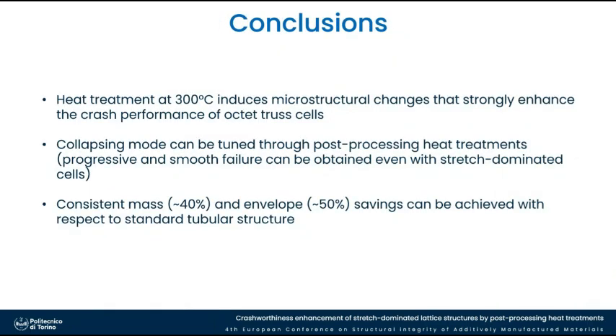So to conclude, the treatment at 300 degrees is able to change the microstructure of the material, and this allows the enhancement of the crashworthiness and the energy absorption capabilities, allowing also to obtain a progressive and smooth failure. With the crash absorber that we have designed, as shown here, we have achieved very consistent mass and envelope savings with respect to the standard structure that is usually adopted, that is shown in the figure.